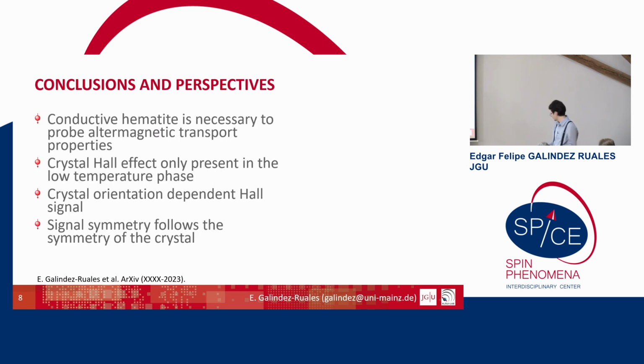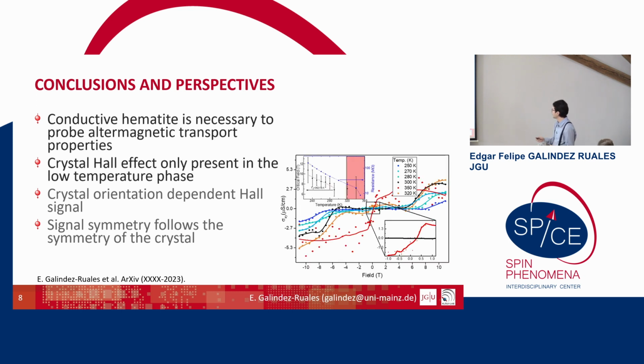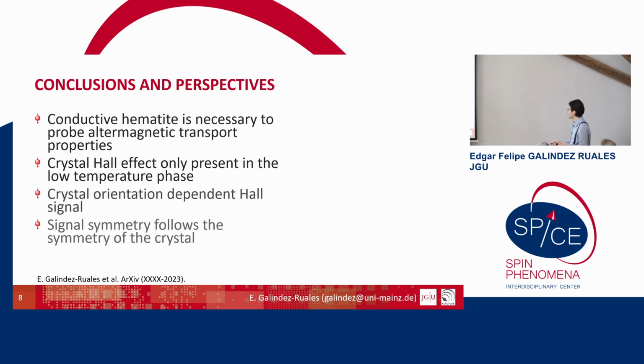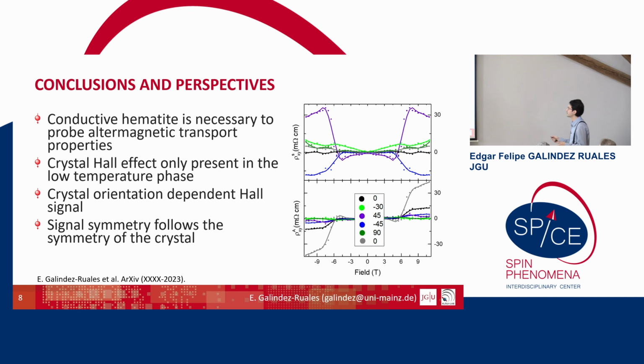So as a conclusion and perspective, I think I was too fast maybe. I would like to conclude that we need to have conductive hematite. It's necessary to prove the altermagnetic transport properties. We have the crystal Hall effect that is only present in the low temperature phase. In the easy plane phase, we don't measure any crystal anomalous Hall effect. And the crystal orientation dependent Hall signal was quite high. So we have different symmetries of the signal depending on the symmetry of the crystal. And that's the last conclusion: the signal symmetry follows the symmetry of the crystal.